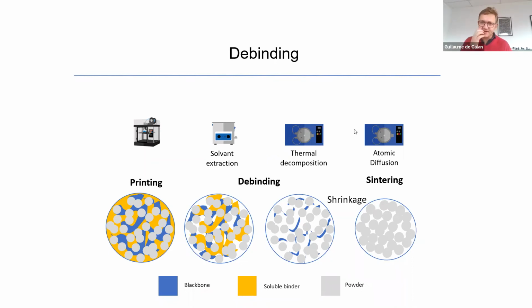So is there a risk of collapsing during the debinding and sintering steps? That would really depend on the materials. When we talk about metal, yes, metals have problems of collapsing and deformation because your sintering temperature is relatively close to your melting temperature, so the metal is soft when you sinter it. In the case of silicon carbide, not at all. The risk is more cracks, possibly deformation due to shrinkage, but cracks are the number one risk, but certainly not collapsing, because silicon carbide is just a material you don't melt, so you don't have this risk of plastic deformation.